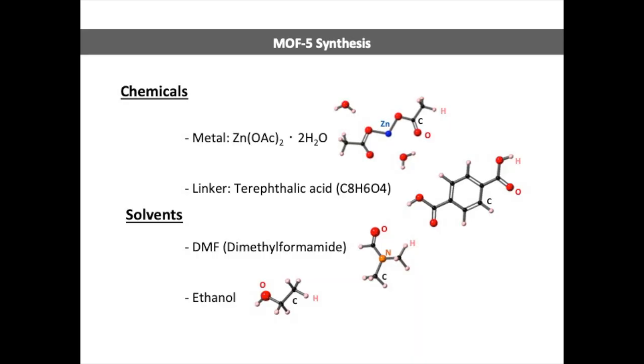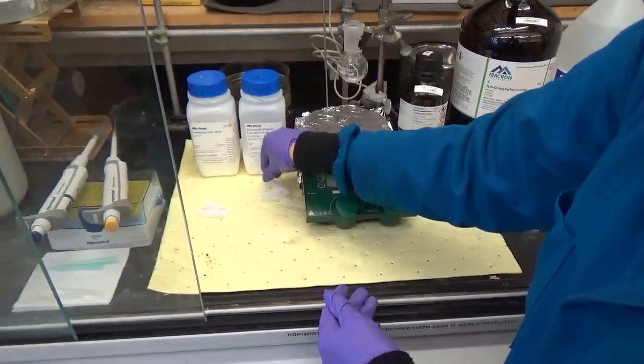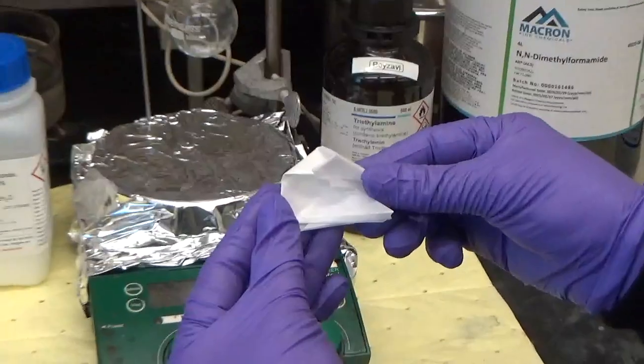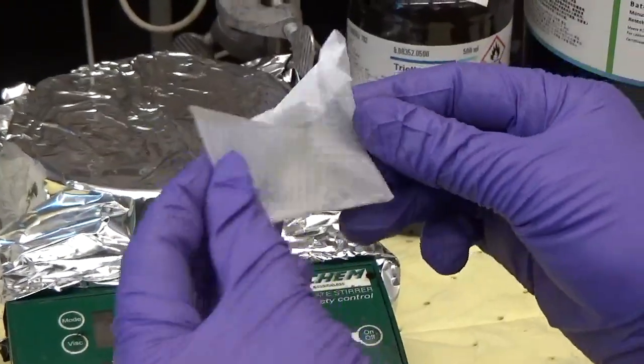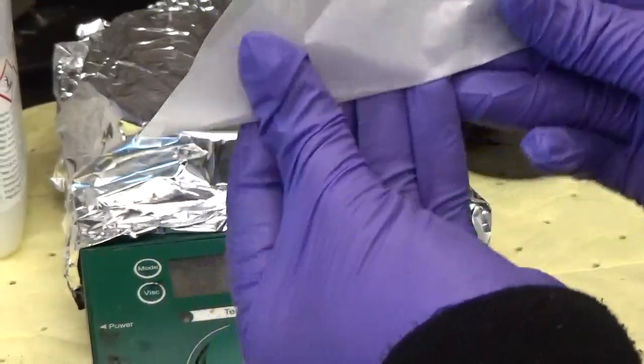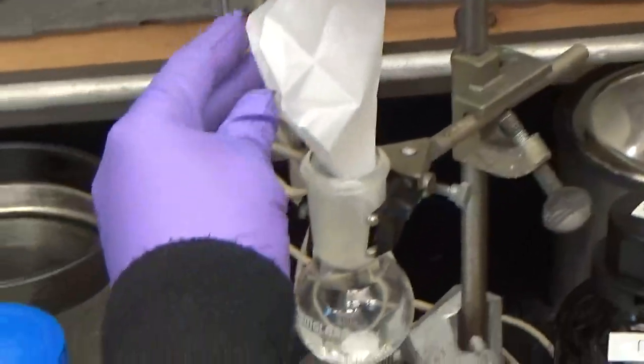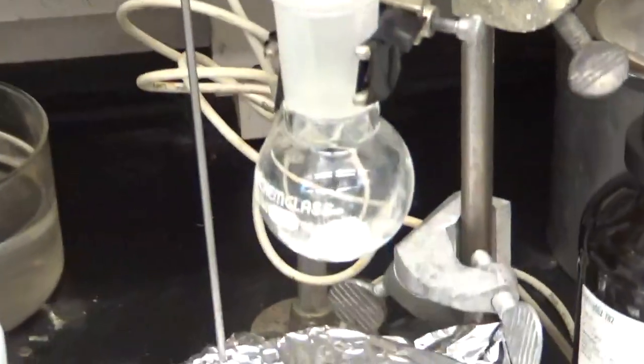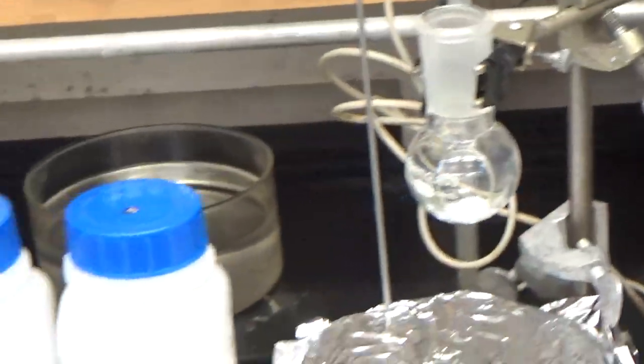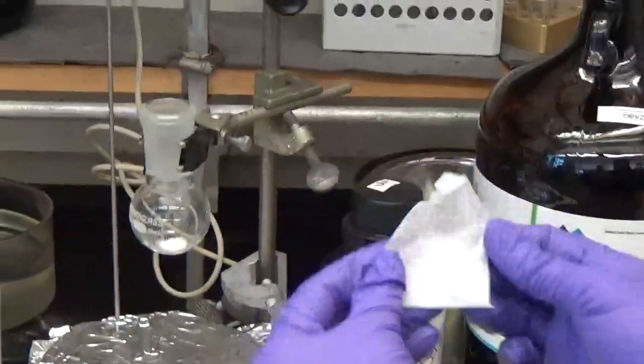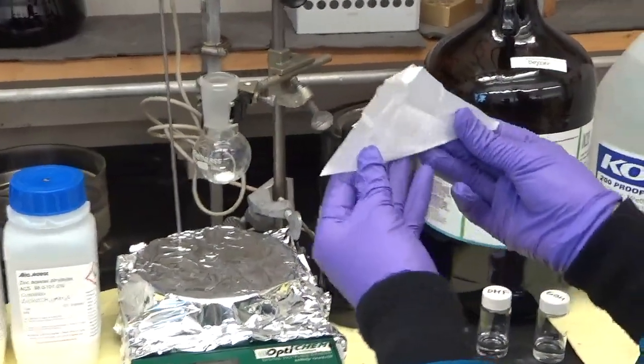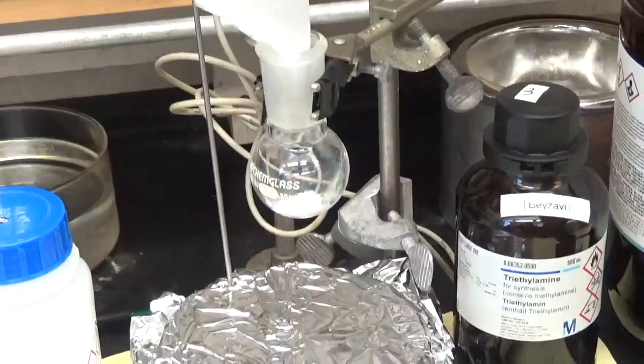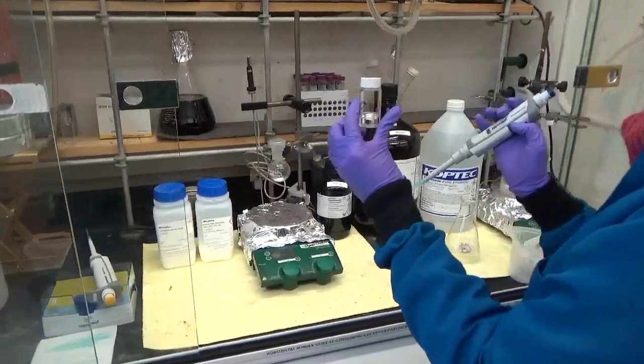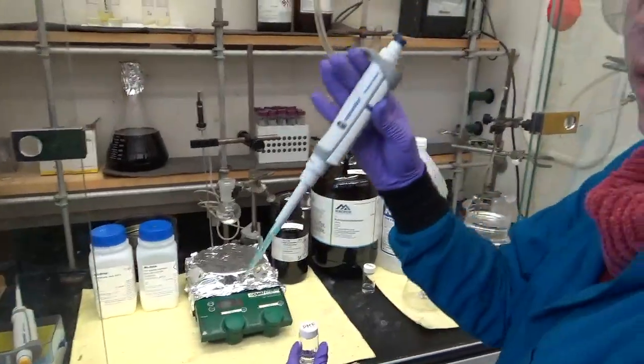So we use terephthalic acid, 25 milligram. I already measured. Also zinc acetate, we need 85 milligram. I already measured. So first, we will pour this material inside of this round bottom flask. Terephthalic acid. I will add DMF 1400 microliter by using a micropipette.